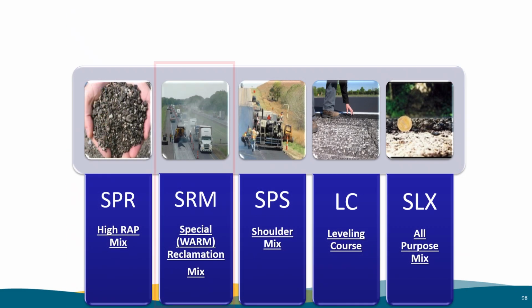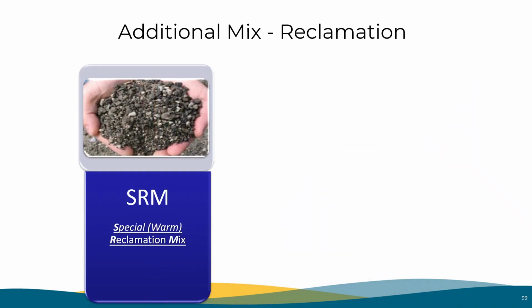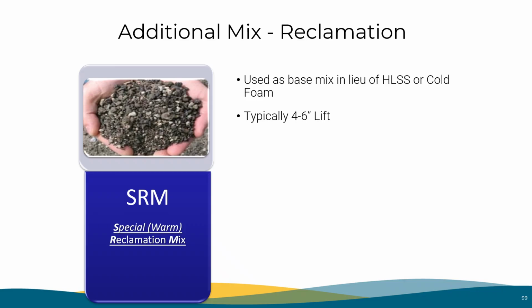SRM is a mix used for deep depth milling and reclamation. It stands for Special Reclamation Mix. Our newest mix, SRM, is a mix used for deep depth milling and reclamation. It stands for Special Reclamation Mix. Used as base mix in lieu of HLSS or cold foam. Typically, it's placed in 4 to 6 inch lifts.